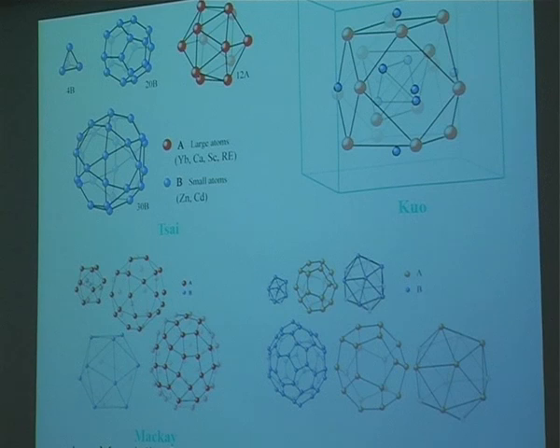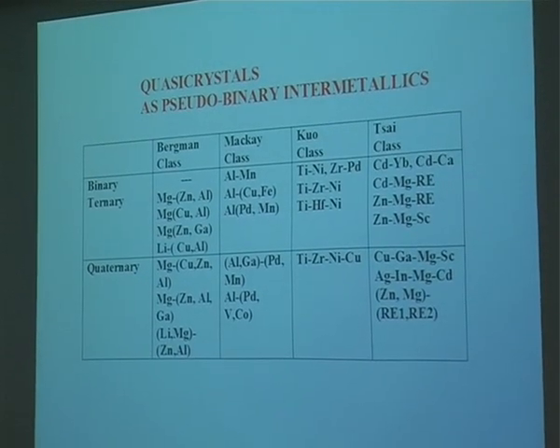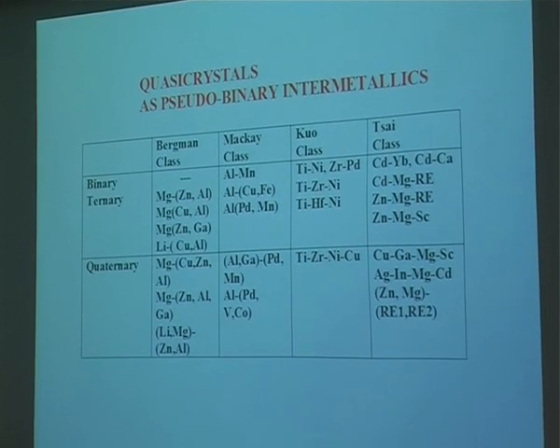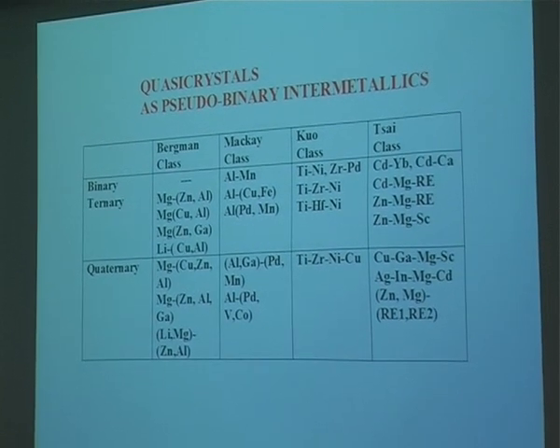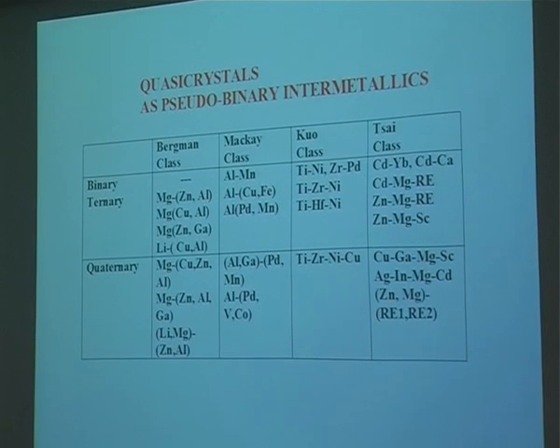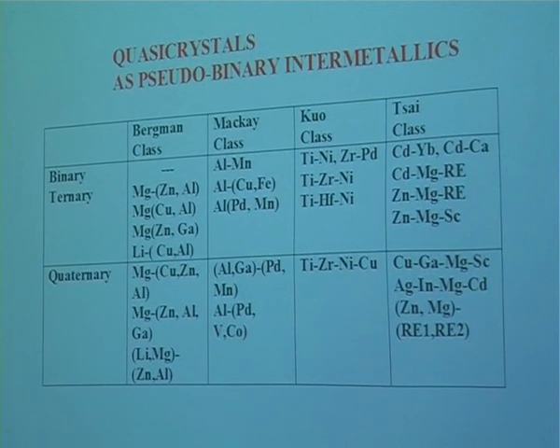So even the question of order becomes easy to understand, because if you had aluminum and gallium, for example, they'll substitute for each other. It is not necessary that they should fit into the same spot in the same way, but certainly they do that. So we have put together here that all quasicrystals can be considered as pseudo-binary intermetallic. Unfortunately, for the magnesium zinc aluminum class, we don't have an existing material. But for the Mackay class, we have aluminum manganese, Kuo class, we have titanium nickel, and the Tsai class, which he discovered, a binary cadmium ytterbium and cadmium calcium. Now, we can replace nickel by zirconium and nickel, hafnium and nickel, so it's possible to build a ternary, quaternary, and even a quinary alloy.